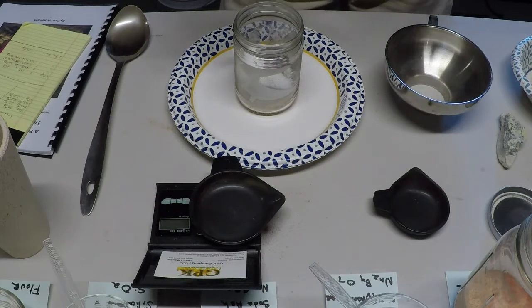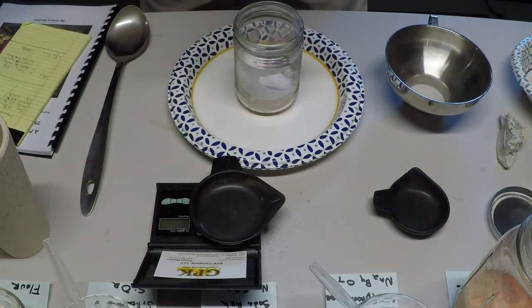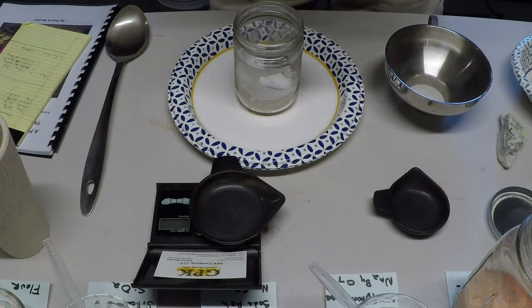The metallic lead will rain through the column of ore, dissolve the gold into it, and collect in the bottom of your crucible. When you pour it into your conical shaped mold, all of the metallic lead, such as this little prill here, ends up in the bottom, and that's where your goodies are. So there's different reducing power of different things. Now this started out as an arsenopyrite. We roasted the ore to get rid of the pyrite and the arsenic. Each one of those is a reducer in itself. Iron pyrite will reduce approximately 11 grams of lead oxide for every 1 gram of iron pyrite, because it is a reducing agent.